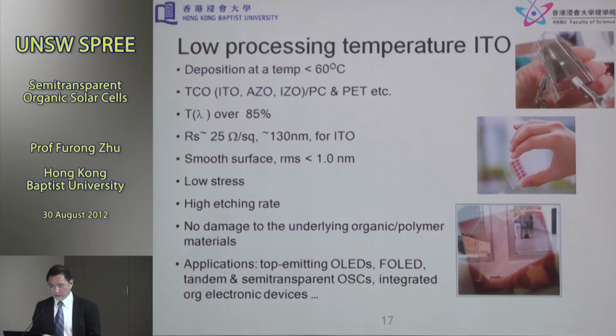Okay, so these are essentially the parameters that we use. And this ITO, using the technique that I just described, can be prepared at a temperature of less than 60 degrees Celsius, and we can use it on plastic substrates for light-emitting devices, for flexible solar cells, and also for semi-transparent solar cells. So these are the parameters: 85% transparency, and for 130 nanometer thick ITO, the sheet resistance is about 25 ohms per square.